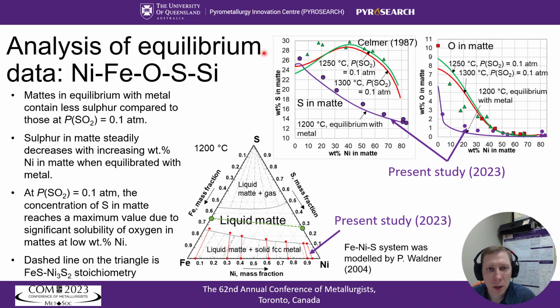On the top left diagram, we can see that mattes in equilibrium with metal contain less sulfur compared to conditions at high PSO2, which is confirmed by literature and reproduced by the thermodynamic model. In case of equilibrium with metal, sulfur decreases monotonously, whereas at high PSO2 it goes through a maximum. The maximum is caused by the significant solubility of oxygen in mattes near the low nickel region. The results of the present study are also projected onto the iron-nickel-sulfur triangle, which clearly shows the sulfur deficiency when compared to the FeS, Ni3S2 stoichiometry.